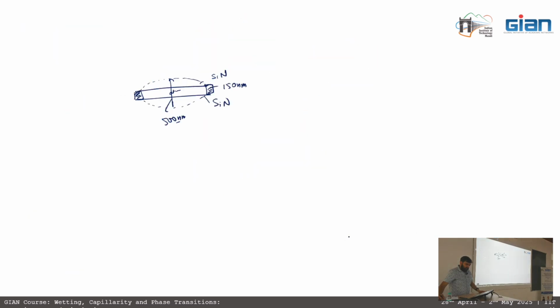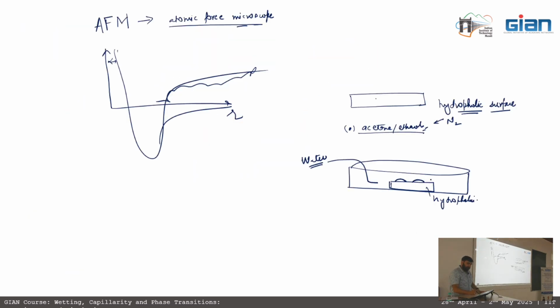Yes, so then these bubbles of pancakes are formed, and then we put the same sample inside. Since this is a wet sample, we have to put it with the petri dish itself. So we put the sample inside a dish, we have water filled in it, and then we have bubbles, and then we use the AFM to raster scan this surface, and we get both the lateral as well as the height of these bubbles. One advantage of using this AFM method is that it gives us a 3D picture.